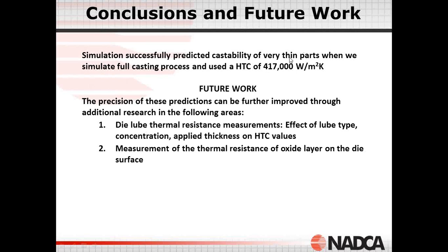So the conclusion is clear that this accurate measurement of 417,000 watts per meter squared K was absolutely required in order to be able to have simulation predict these cold flow defects.